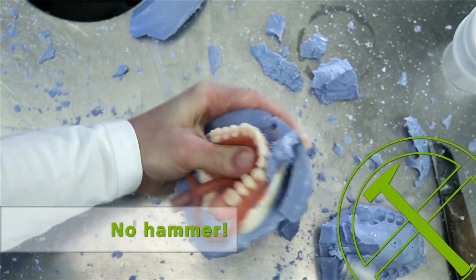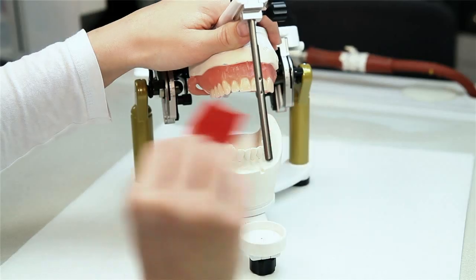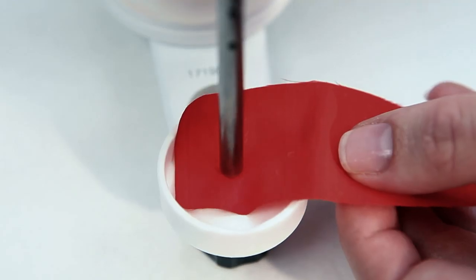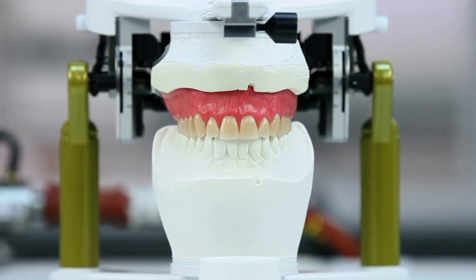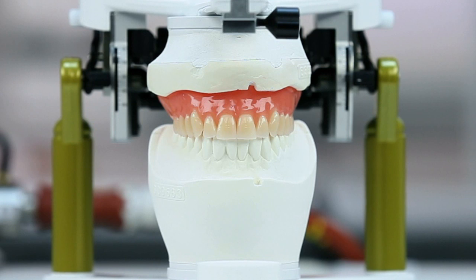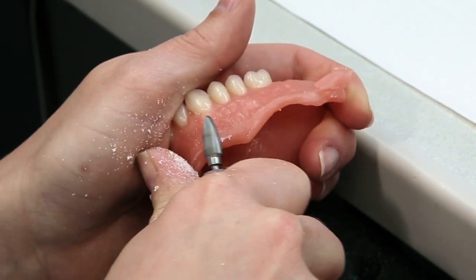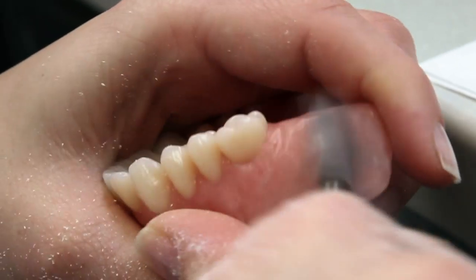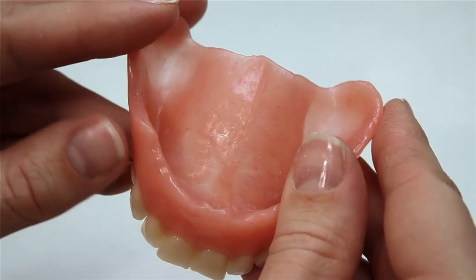Do not use a hammer for divestment, since this may damage the dentures. Due to the coordinated system components and the shrinkage-compensating polymerization process, there is no increase in vertical dimension. The surface of the resin is a one-to-one copy of the previous wax-up. The polymerized IvoBase material is finished as usual with cross-cut tungsten carbide burrs, sandpaper, and polishing media. Please refer to the instructions for use for the repair, extension, and relining procedures.